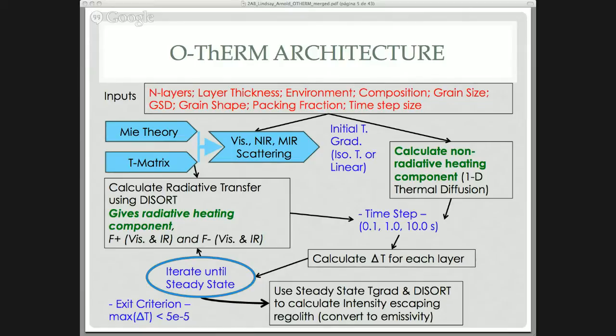What you do is throw all these inputs in and start with an initial temperature gradient. This is where the code is modular. You can calculate your scattering parameters, the single scattering albedo, your phase functions, and your optical depths, using Mie theory or T-matrix. T-matrix allows us to do a little bit of grain shape exploration. That'll give us our visible, near infrared, and mid infrared scattering. Then we can toss that into DISORT, let it handle the scattering through the regolith, and that will give us our radiative heating component. Simultaneously, we're calculating the non-radiative heating component. This is just a 1D thermal diffusion. No reason to talk about that more; it's been discussed at length here at Thermops.